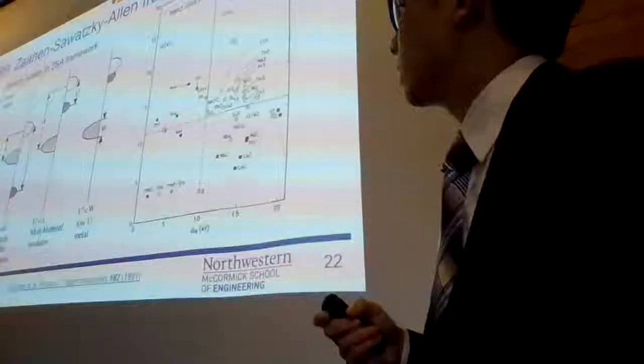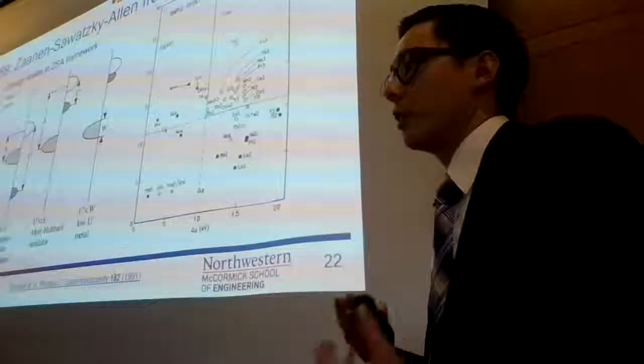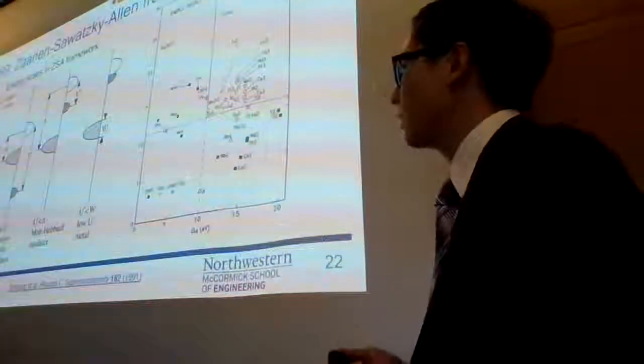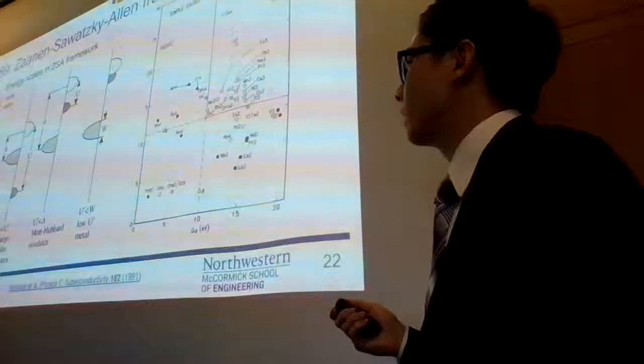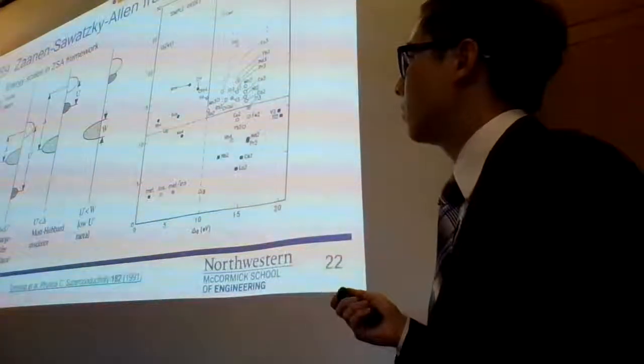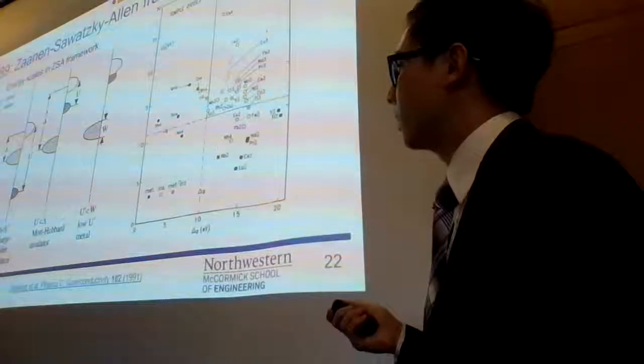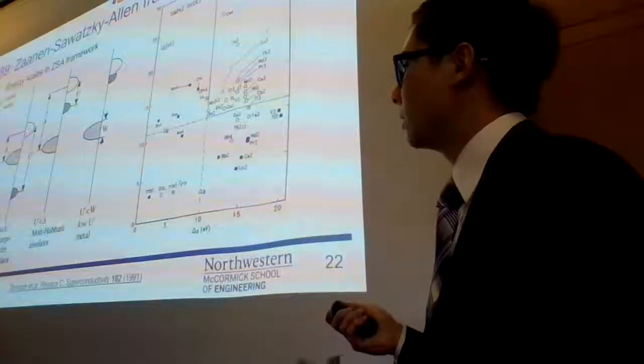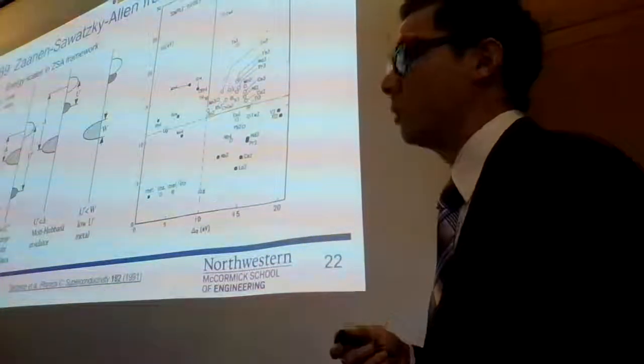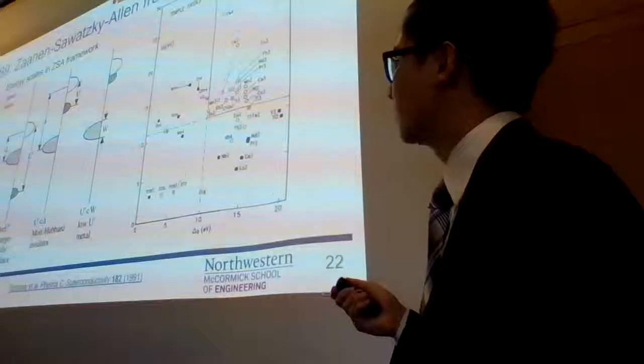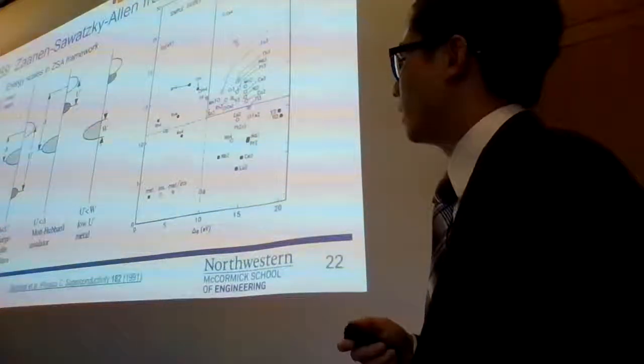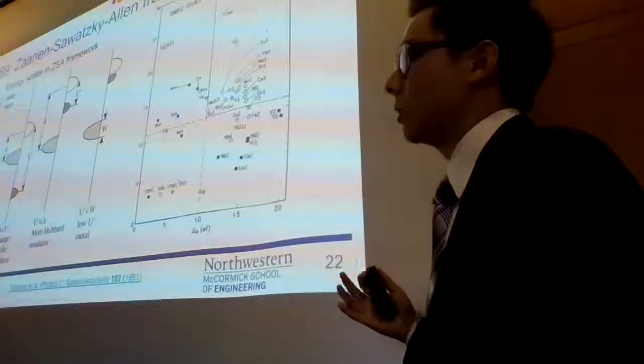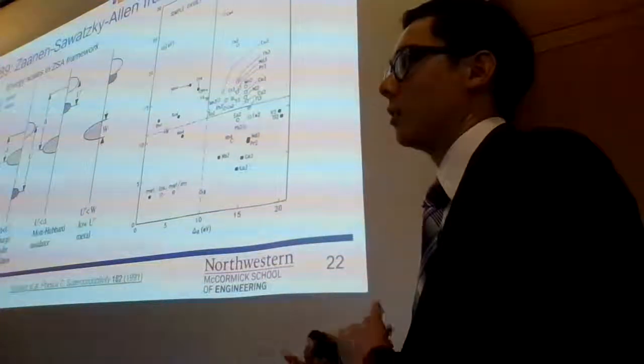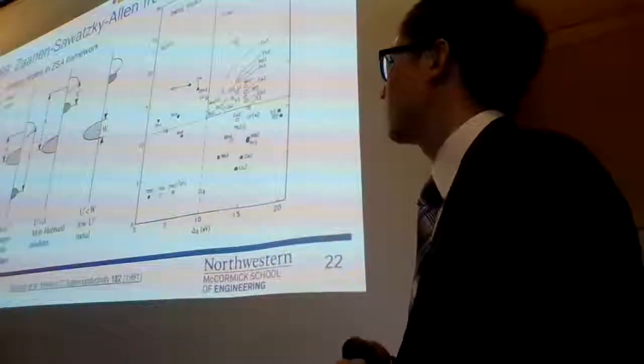So they essentially reason that there are two ways you can achieve conductivity in a correlated transition metal oxide. You can have electrons excited from an occupied metal orbital to an unoccupied metal orbital, or you can have an excitation from, say, a ligand orbital to an unoccupied metal orbital. So this charge transfer parameter, or this U parameter. And they figured out a way to estimate this using, say, ionization energies and Madelung site potentials, and just structure.